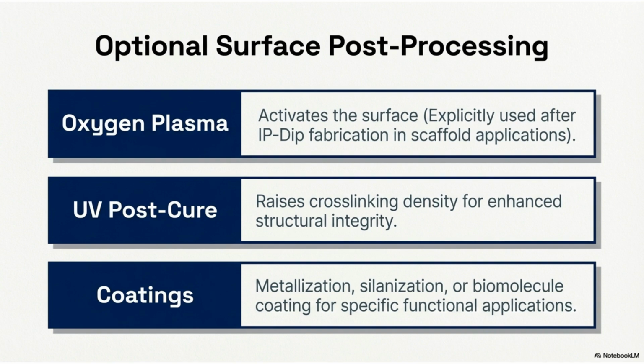Optional surface post-processing steps include oxygen plasma to activate the surface, UV post-cure to enhance structural integrity by raising cross-linking density, and various coatings like metallization for functional applications.